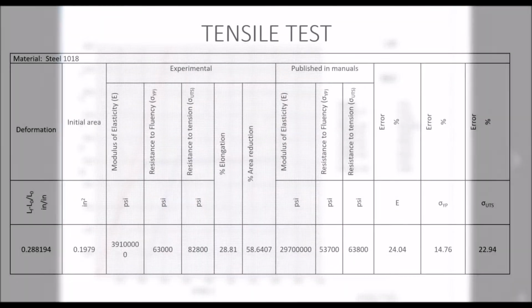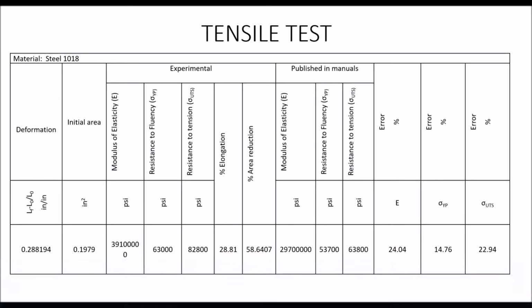I investigated the mechanical properties of this material. I investigated this data from the American Iron and Steel Institute, and the values that I got were 29,700,000 psi for the modulus of elasticity, 53,700 psi for the resistance to yield, and 63,800 psi for the resistance to tension.